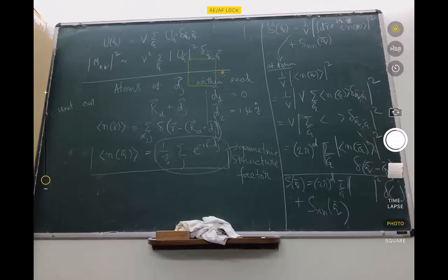So atomic form factor comes from the fact that different atoms can give different scattering potential to the particles. And this thing, geometric structure factor, comes in simply because you may have, in some situations, more than one atom in your basis. Otherwise, on the right, what you have is the general analysis of the situation.